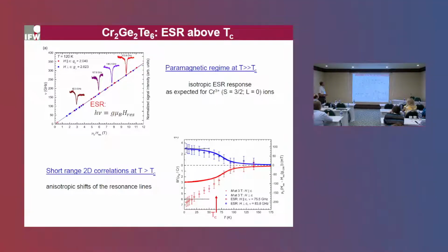Now if we measure electron spin resonance in the paramagnetic state far above the phase transition, we can measure at different frequencies, and the response is very isotropic. The resonance lines are very sharp, and the slope of the frequency-magnetic field dependence gives us the g-factor value, which is very close to the spin-only value expected for the chromium 3+ ions because they don't have an orbital momentum in the ground state. However, there was a first surprise: as soon as we lower the temperature below 120 Kelvin, this response gets progressively anisotropic. The resonant field for the out-of-plane direction goes one way, and the resonant field for the in-plane direction goes the other way.